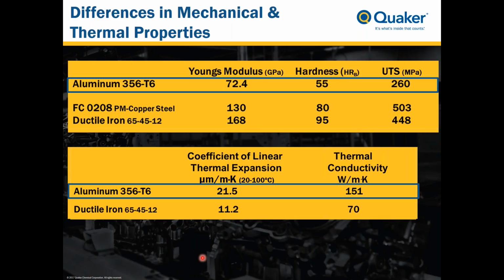And again, what you can see is that as the aluminum heats up, it's going to expand considerably more than the ductile iron will. So as you're machining a bore that contains a ferrous metal, the ductile iron, and the aluminum, and you start to generate heat during the cutting process, during deformation, during friction, you're going to have the aluminum start to expand much greater and at a much greater rate than the corresponding ferrous component. And again, what this presents is some unevenness in the bore that's being machined, different flexure properties, some deflection that can occur, and ultimately some very, very real machining challenges.